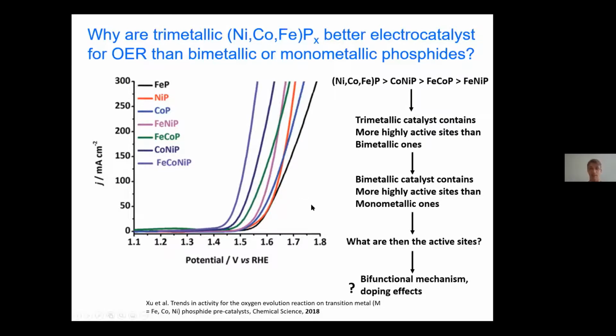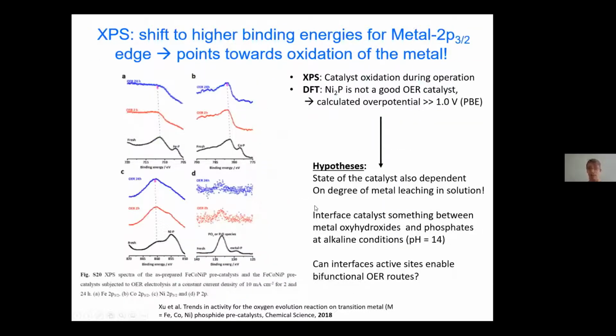So what are then the active sites? We could see what happens with these phosphide precatalysts. During catalysis, from a shift in the XPS spectra of the 2p metal edge, we see a shift to the left for all metals. That means they are oxidized. So the real catalyst we find under operating conditions will probably not be a phosphide, but more something like a metal oxyhydroxide with some phosphate ligands rather than a pure metal phosphide catalyst.